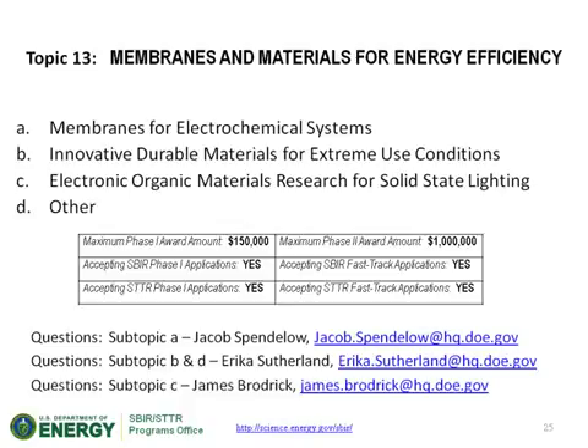A lot of the commercial applications involve the use of polymers and composites, and we're trying to understand in more detail how the materials behave in these extreme conditions. Some of the information we're looking for is hydrogen uptake, degradation mechanisms where possible, and trying to extend the service life of these. In some cases, for instance with hoses or seals, we're having to change them out after only about a third of their target service life. So improvement in those areas, as well as gaining a fundamental understanding of the materials' behavior, is what we're looking for.